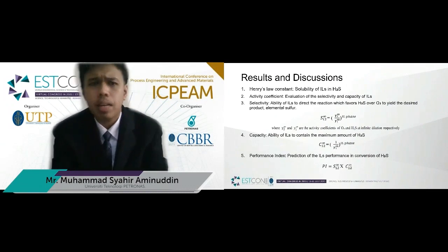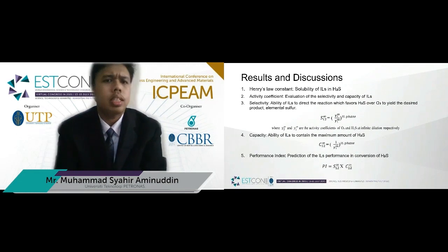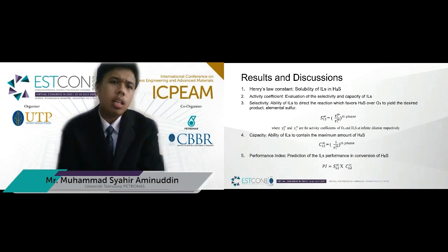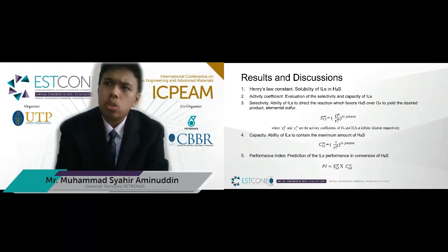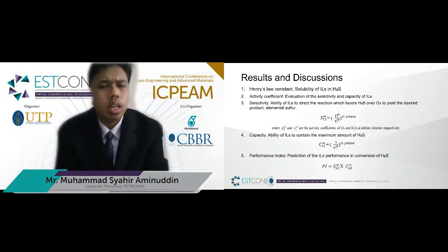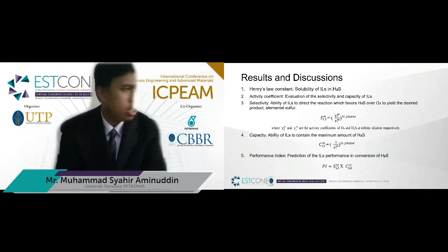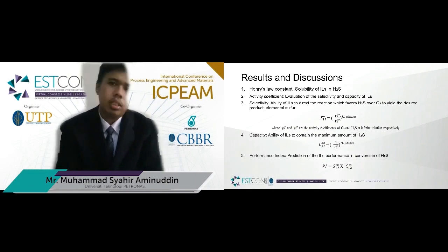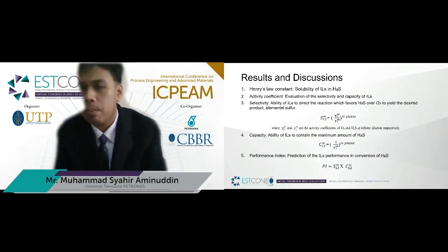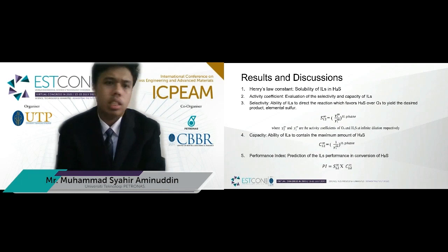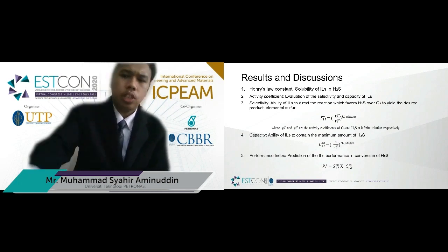Basically, there are 5 major parts for the results and discussion. The first one is the Henry's law constant, which is to determine the solubility of hydrogen sulfide in ILs. The activity coefficient is to evaluate the selectivity and capacity of ILs. Selectivity refers to the ability of ILs to promote the reaction which favors hydrogen sulfide over oxygen to yield the desired product, which is elemental sulfur. And capacity refers to the ability of ILs to contain the maximum amount of hydrogen sulfide. And last but not least is the performance index, where we predict the IL's performance in the conversion of H2S.